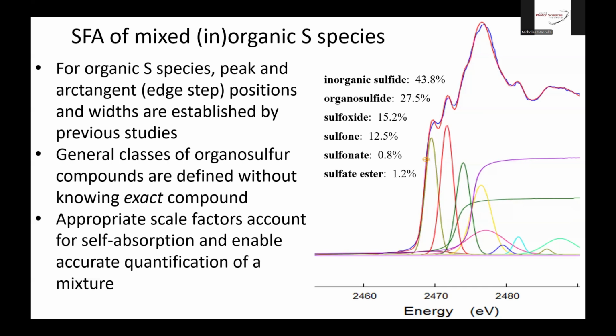So then you can fit the spectrum with components that you know come from known species, and then apply a scale factor appropriate to account for self-absorption, and you get a nice quantification of what's actually in your sample. And so this is really a powerful tool, and it's not susceptible to artifacts like linear combination fitting. And you don't necessarily have to know the exact chemical species and have a perfect spectrum of it in order to fit it. So that's a really powerful tool for analyzing mixtures of different species.